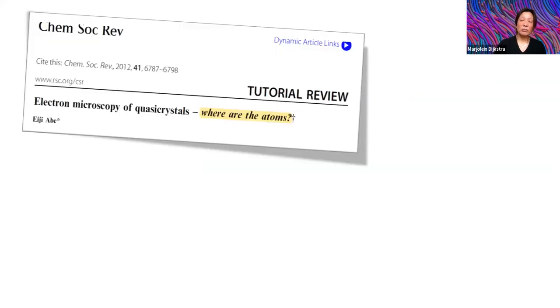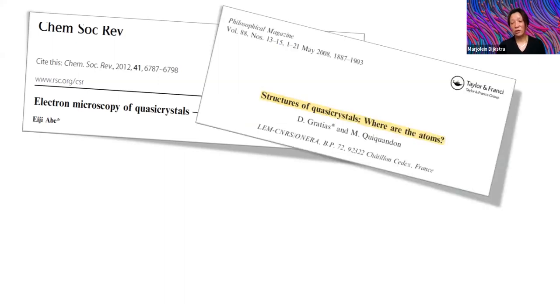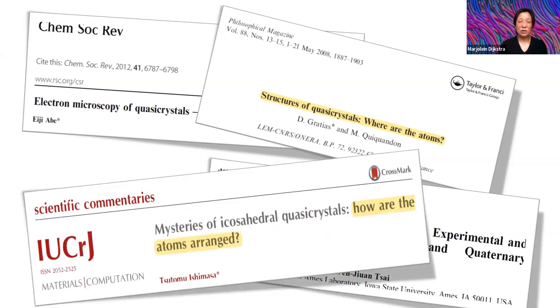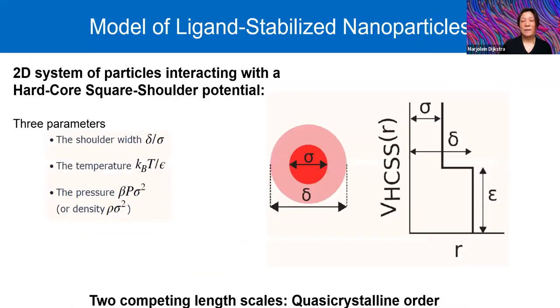So there are many papers in the literature asking: where are the atoms in quasicrystals? How are the atoms arranged? And so it would be very nice if we can inverse design the quasicrystal and we know exactly where all the atoms are. So the system that we took is a very simple model of ligand stabilized nanoparticles. It consists of a hard core with a diameter of sigma and then a square shoulder with a range of delta. So the three design parameters that we have are the shoulder width, the temperature, and the pressure or the density. And because this interaction potential has two competing length scales, it gives rise to quasicrystalline order.